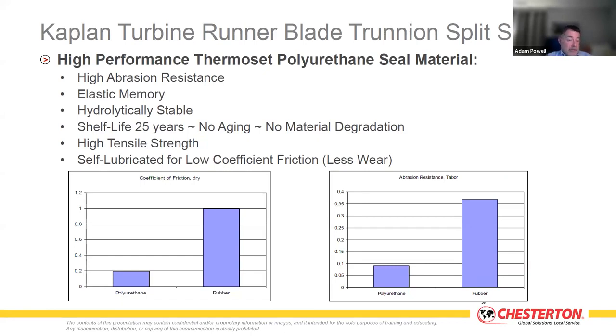Oh, and this: high abrasion resistance, elastic memory, hydrolytic stability. Now, this is a key piece. We do a tremendous amount of work for the US Navy. One of their challenges was that by the time they make an order, receive it, put it into their store system and distribute globally, shelf life was an issue, certainly for a lot of the rubber components, the soft components. It would take them more than 3 years to get product into the stores facility. At that point the shelf life was close to expired, so they had to replace it before they even used it. The urethane has a 25-year shelf life, no aging, no material degradation.